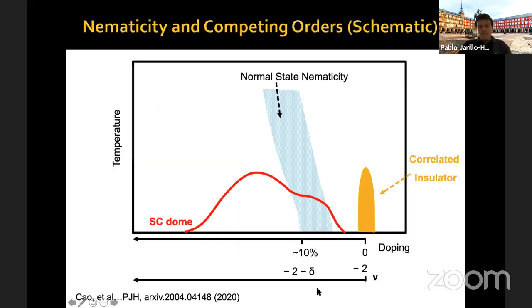So the thing that is becoming clear is the following. This is how the picture is evolving. In the phase diagram of magic angle graphene, around 2 holes per moiré unit cell, we have a correlated insulator state. Now, in some angular range, we see this behavior again for samples which have typically pretty high Tc, so around 1.07 degrees plus or minus 0.03 degrees, more or less, okay?